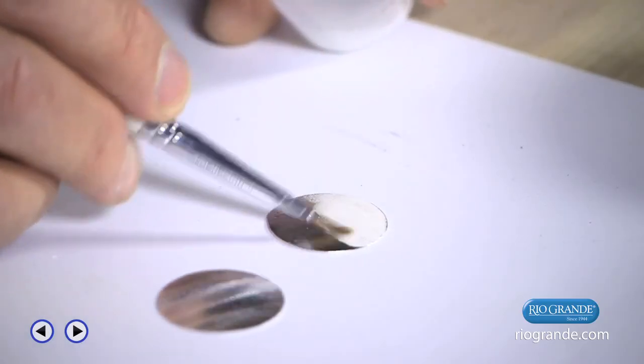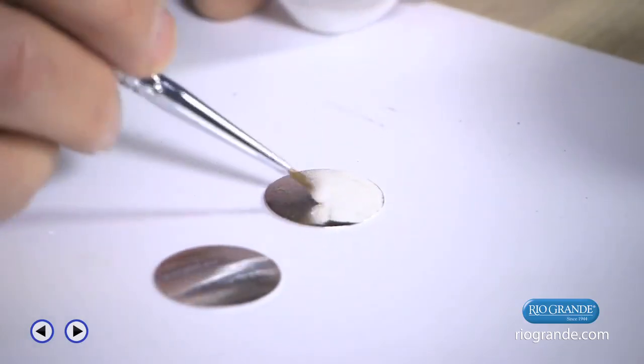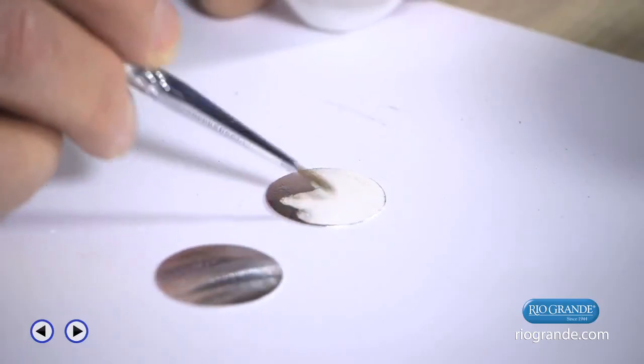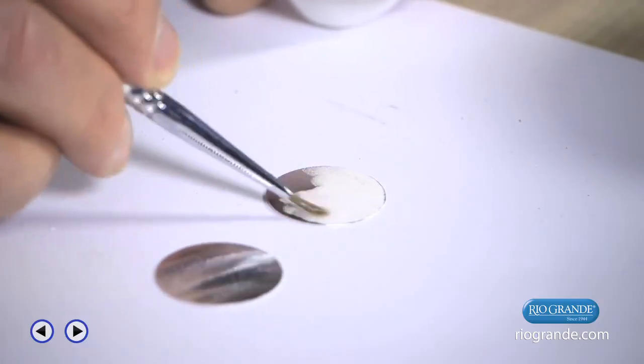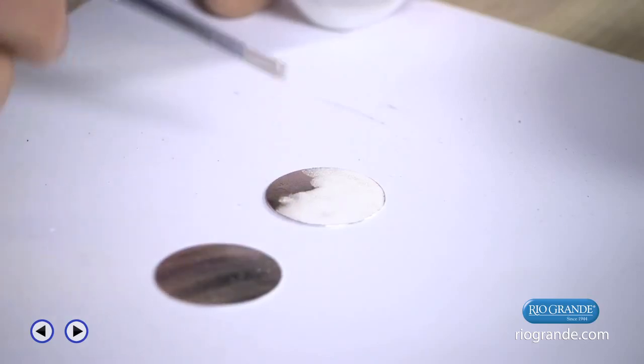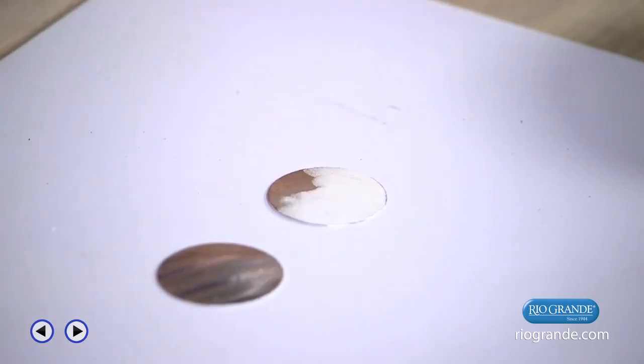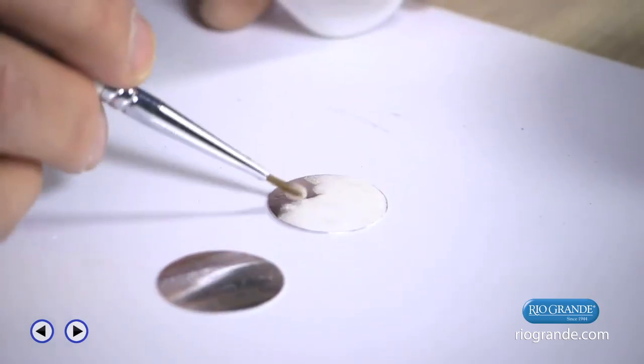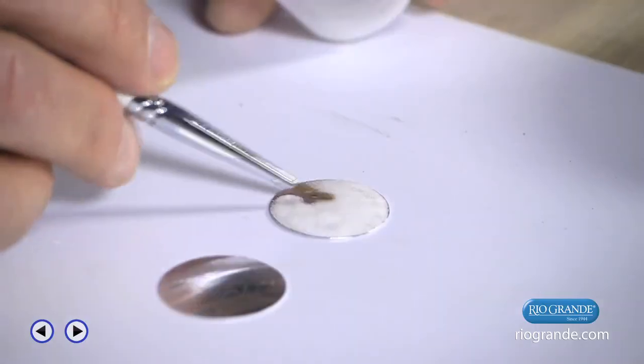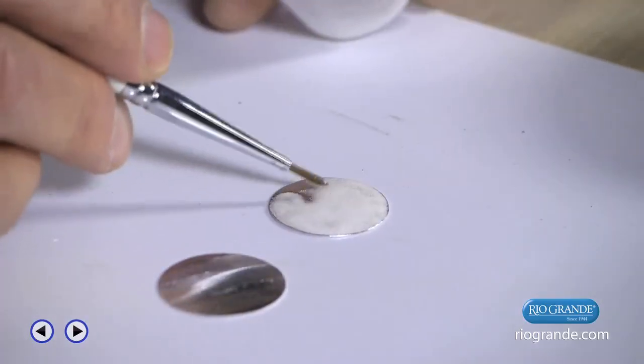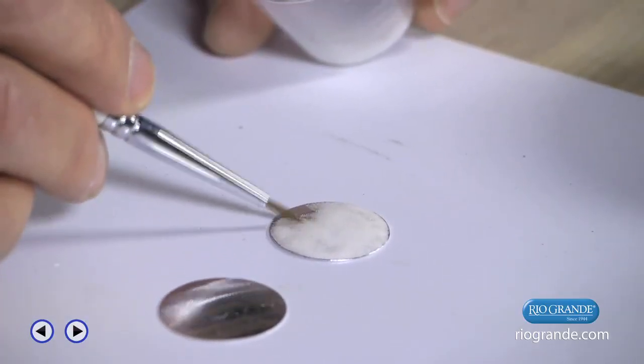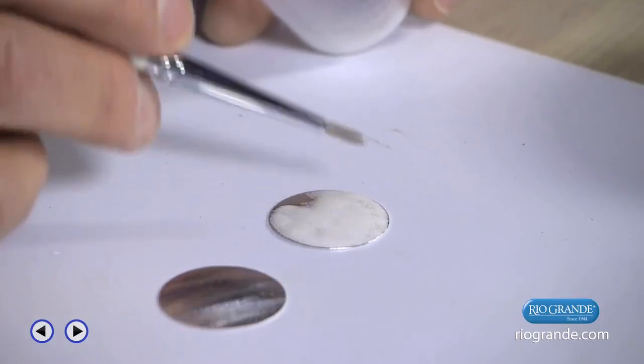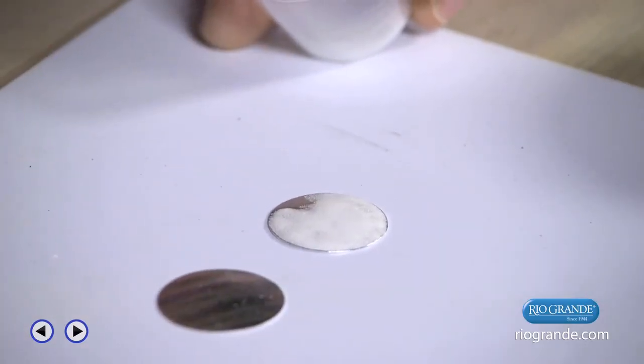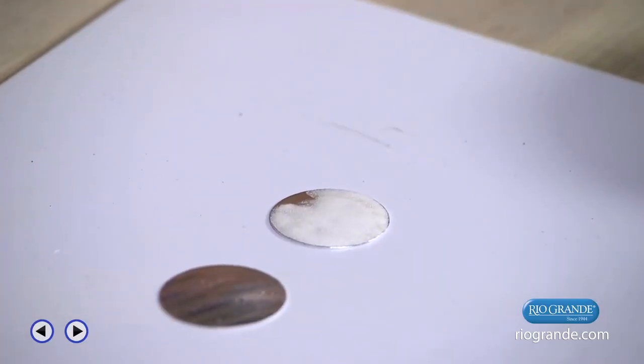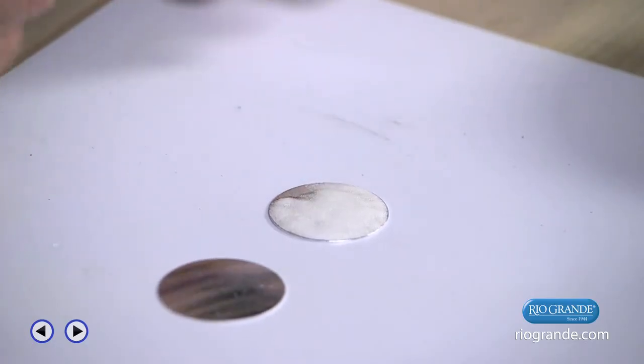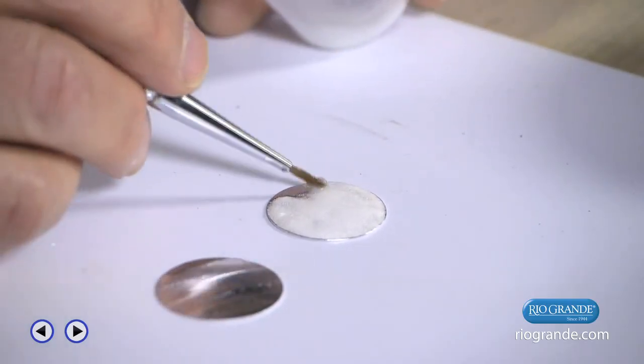And what I'm looking for is a nice even coat. But instead of obsessing about it right now, I'm just going to consider this my layout process, and I'm going to try to get enamel on the piece, and then I'm going to go back and make sure it's not too thick or too thin. Because as I said before, too many air bubbles makes your enamel cloudy. And the thicker this layer, the more grains of enamel, the more air bubbles. So if I get it too thick, I'm going to have too many air bubbles, and it's not going to be clear.